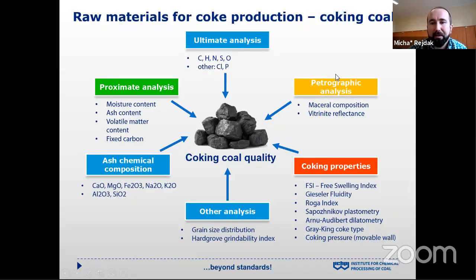A very important thing is petrographic analysis, because coals contain macerals like vitrinite, inertinite, or liptinite, and different kinds of macerals act in different ways during the pyrolysis process. And of course, for the coking process, very important parameters are the so-called coking or caking properties, like free swelling index, Gieseler fluidity, Roga index, Sapozhnikov plastometry, Audibert-Arnu dilatometry, Gray-King coke type, or coking pressure, which can be determined in a movable wall oven.